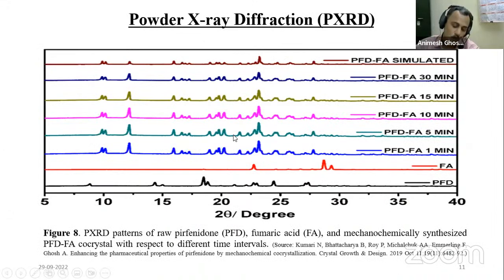So if we do the XRD, now what we have done, because we need to prepare the formulation, our aim is to prepare bulk amounts. Bulk means at least per batch, if we can produce 500 mg, 1 gram, then it will be useful for us. So we have tried mechanochemical synthesis. In mechanochemical synthesis, grinding time is very important, right? So after getting this, that is the simulated pattern. That means if you get the single crystal data, from the single crystal you will get a simulated XRD pattern. Then we tried to find the minimum time required to get the co-crystal by milling.